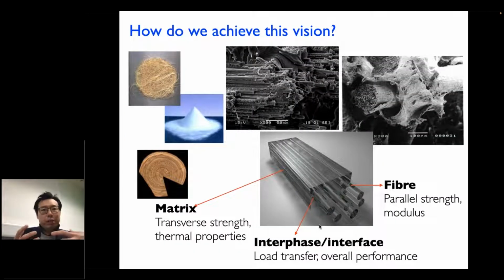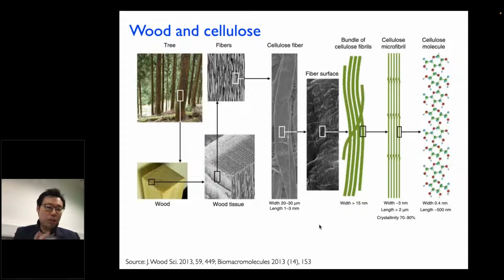So how do we achieve this? Effectively, we are going to use a composite approach, right? That you actually combine cellulose, as the reinforcement, with a suitable polymer matrix. Ideally, the polymer matrix should be sustainable. The matrix protects the cellulose fibers. The fibers carry the stiffness, the strength. The interface between the fiber and the polymer matrix is an important design parameter that allows efficient stress transfer to achieve maximum performance.